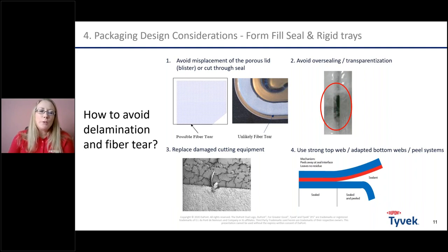Second, oversealing or transparentization should be avoided, because then, for example in case of Tyvek, you bake the Tyvek to the film, right? In terms of cutting, you should always ensure that your slitting equipment is not damaged, especially if you need to cut through the seal for whatever reason. And then finally, obviously, the strength of the top web plays always a role, and the selection of the adapted bottom web or film or coating, what we have just seen before.